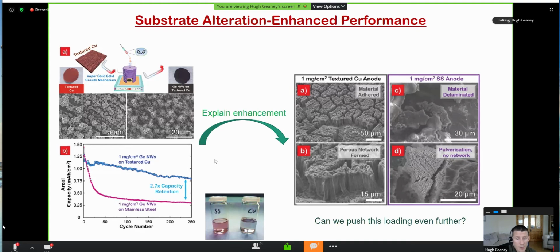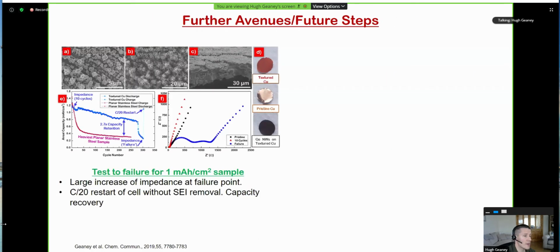So the next question then became, can we push this loading even further? So I had quoted 3 milliamp hours per centimeter squared as a potential target. So I'll show that in 1 second. But one issue is that people don't necessarily test their materials to failure. So what we found here is when we continued on beyond the 250 cycles, that we had this abrupt failure mechanism that seemed to occur just before 300 cycles. So when we looked at this with the EIS, then what we found is we had a major impedance increase at the failure point.